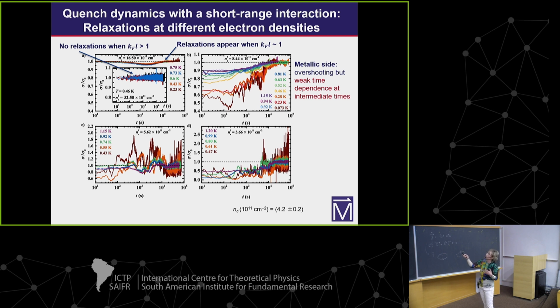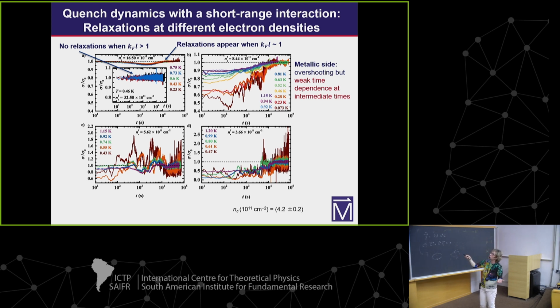Then we start approaching, still on the metallic side, but approaching the metal insulator transition. We see behavior similar to what I showed on the previous slide: negligible relaxation initially, or at intermediate times, and then basically the same equilibration time. As you get close to the metal insulator transition, the noise becomes huge.